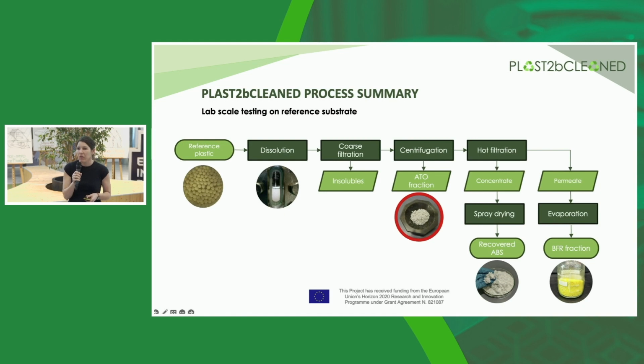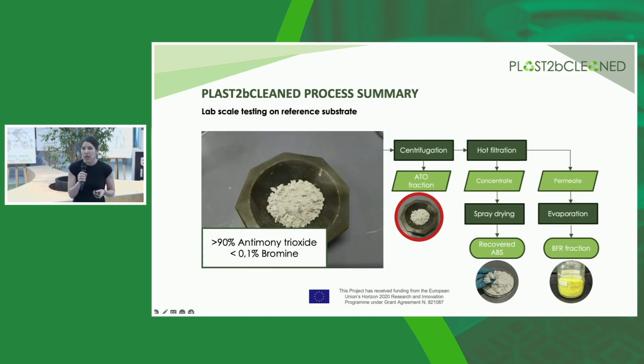Permeate, which after evaporation provides the soluble BFR fraction, and from the concentrate, after spray drying, we can recover ABS or HIPS or whatever polymer we focus on in this process. For antimony trioxide, as already mentioned, here on the picture you can see the nice white powder recovered from the reference material. It was of high purity with a low bromine content.